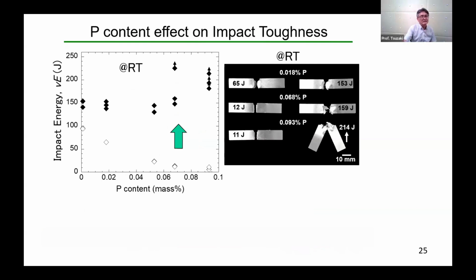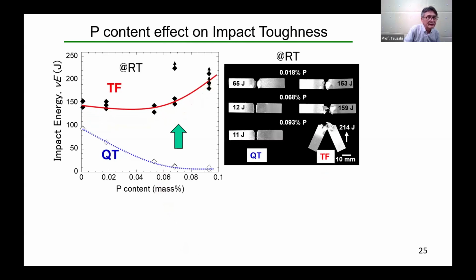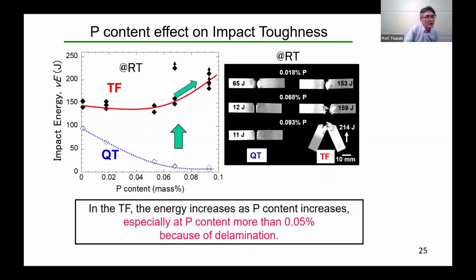Now, this slide shows the result of the impact test that you have been waiting for. As shown in the introduction, the impact energy decreases monotonically with increasing P content in the QT material, like this. On the other hand, in TF material, impact energy increases as P content increases, especially at P content more than 0.05%. In the TF 0.093% P still, significant delamination occurs as expected.